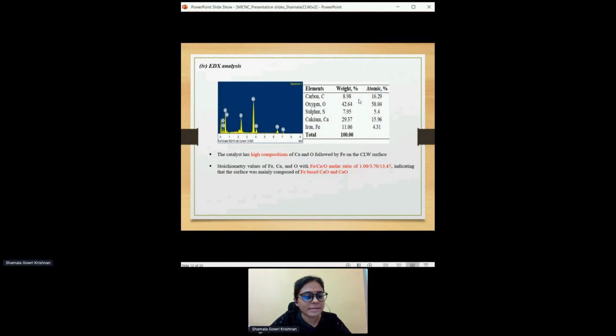Followed by the EDX analysis, we found that this catalyst has a high composition of calcium and oxygen, followed by iron and also sulfur. We do have sulfur, and by the molar ratio of iron, calcium and oxygen, we found that this catalyst is composed of iron-based calcium oxide and calcium oxide.